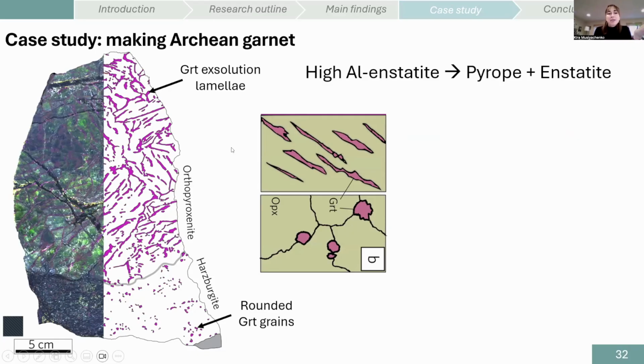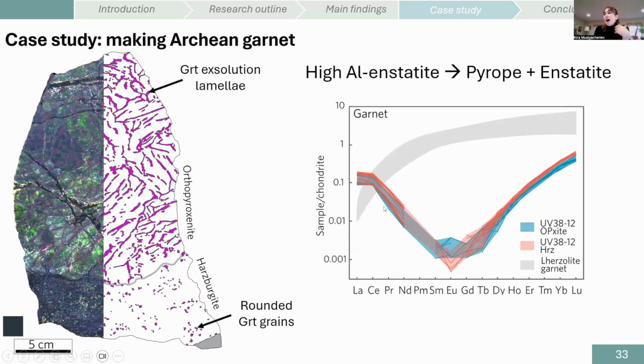Usually with mantle samples, it's really difficult to determine whether garnet is a primary phase or was introduced metasomatically. It's really hard to argue for one or the other, but in this case, the texture leaves no ambiguity. We know that those garnet lamellae were exsolved from the enstatite. That process happens via exsolution from a high-aluminum enstatite protophase when it becomes unstable during cooling or pressure increase. As a result, the exsolved garnet here has inherited the rare earth element composition of a very depleted enstatite. Remember, enstatite has very low distribution coefficients for most of the elements. And garnet, which normally would like to incorporate these elements, is left with nothing because it exsolved from an enstatite phase that originally had nothing.